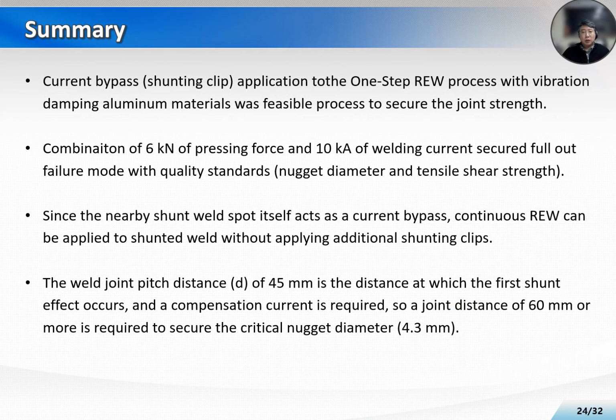Here is the summary of this research. Current bypass shunting clip application to the one-step resistance element welding process with the vibration damping aluminum materials was a feasible process to secure the weld joint strengths. A combination of 6 kN of pressing force and 10 kA of welding current secured full pull-out failure mode and quality standard, from nugget diameter and tensile shear strength perspectives.